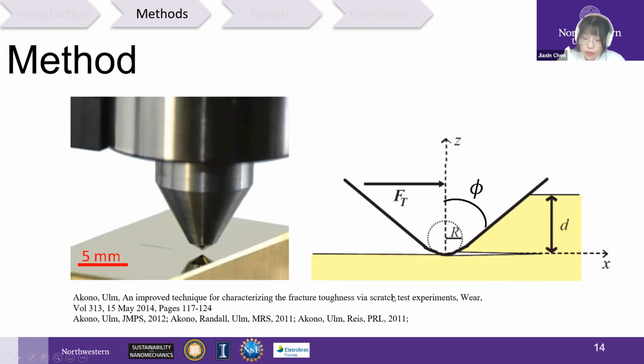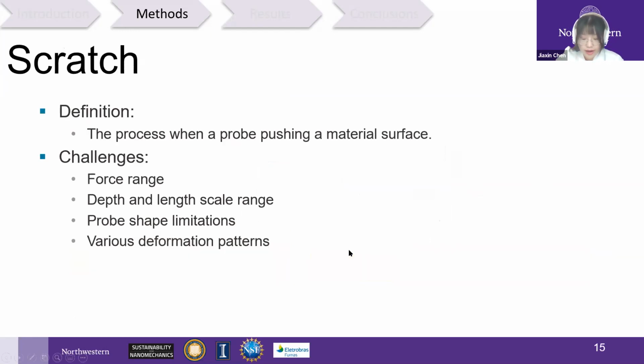Our tests were carried out using a Rockwell C probe that consists of a cone of half apex angle of 60 degrees, which is the theta here on the right-hand side figure, ending in a sphere of tip radius R equals 200 micrometers with a sphere-cone transition depth of 27 micrometers. The challenge here is to carefully prepare a specimen of ASR gel crystals and design the experimental parameters that can be tested using scratch testing and satisfy the assumptions for obtaining the fracture toughness.